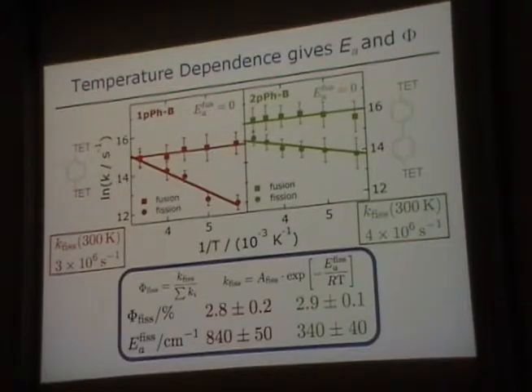So we do Arrhenius plots, right? We measure the rates as a function of temperature, forward, reverse rates. We find that the reverse rate, the fusion rate, is not activated. This is comparable to what people saw in crystals. The forward rate does seem to be activated.